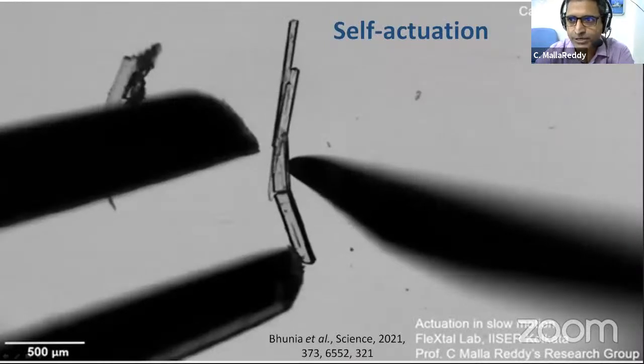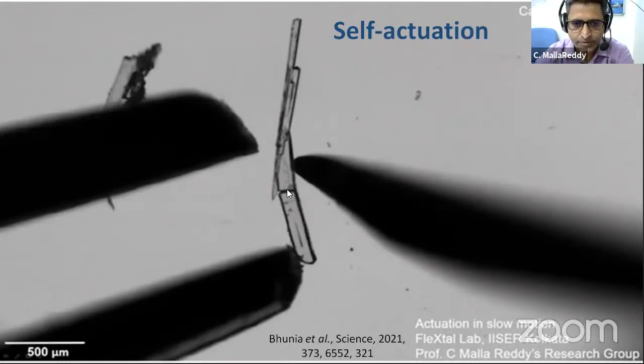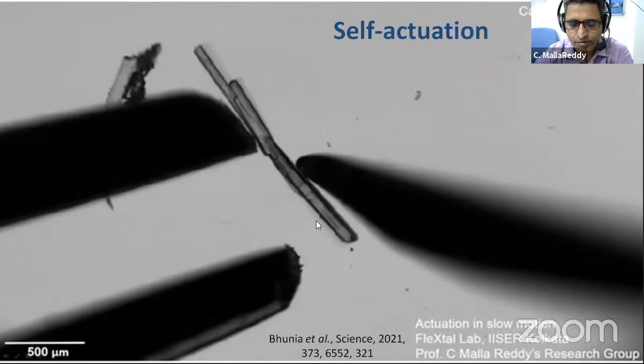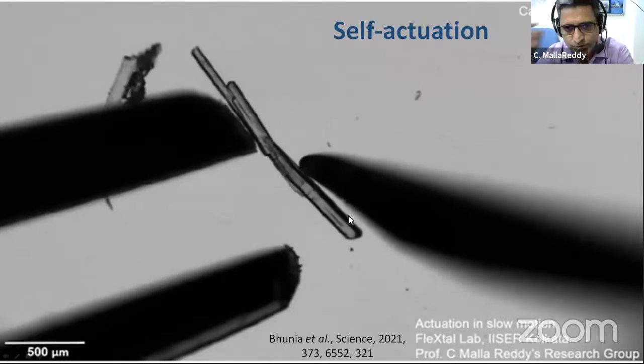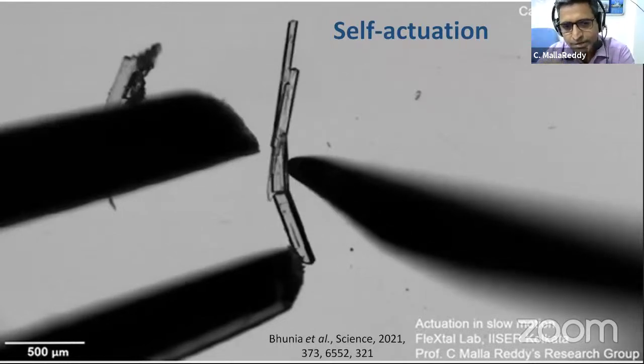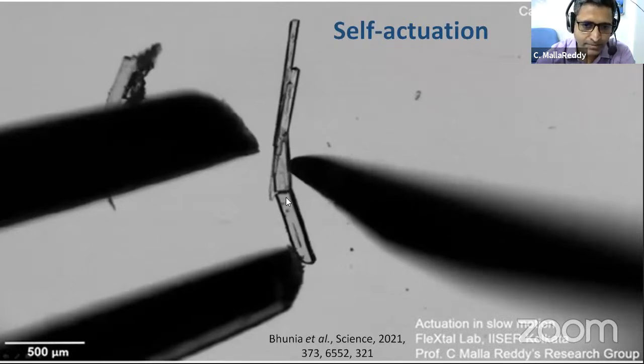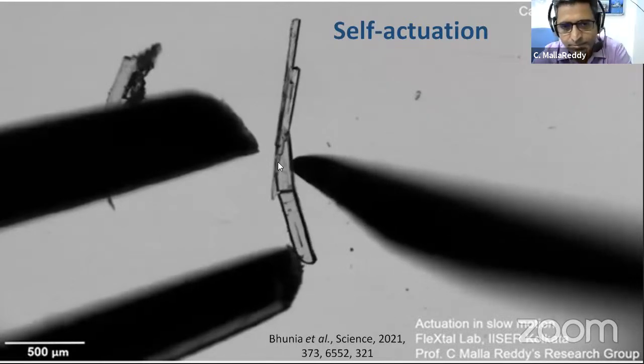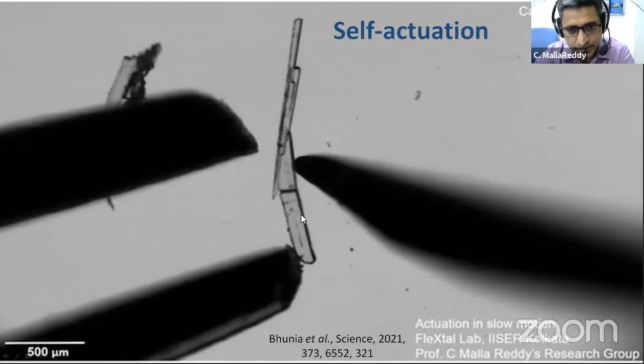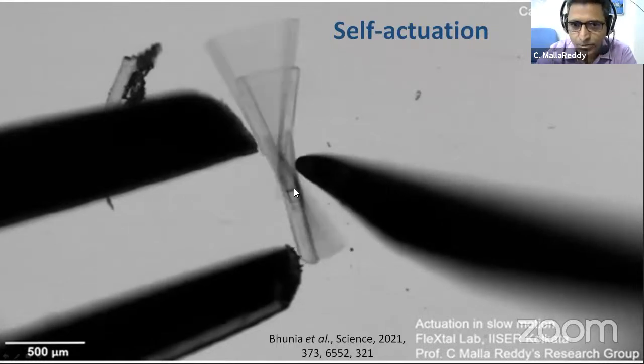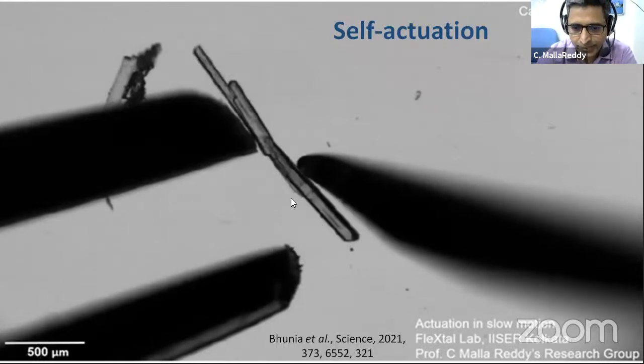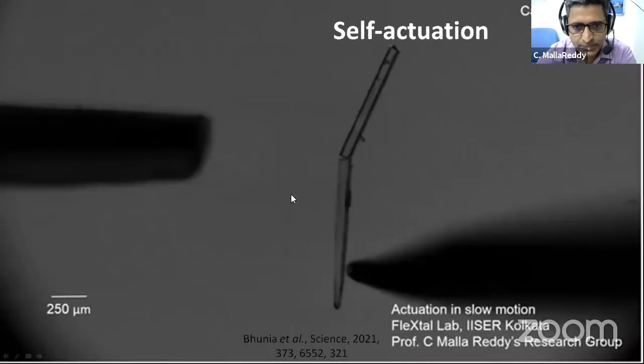Again, this is a slow motion video. It was taken at 500 frames per second. And when you crack and release, there is a lot of attraction, and that leads to a kind of motion. We were very surprised to see this kind of motion. Normally when you release some cracked piece, it just remains there. So this suggests that there is some kind of attraction between the two particles, and that is why they are coming closer. So then we wanted to understand that.